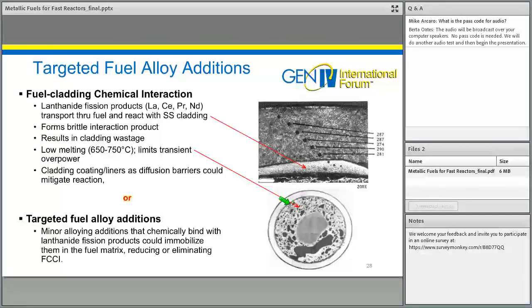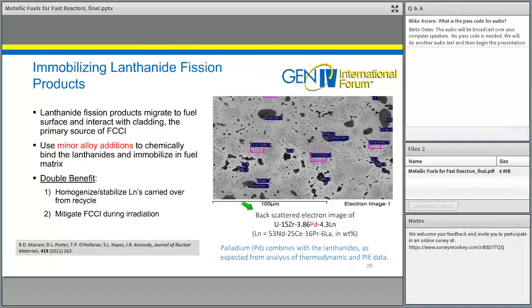These tend to have difficult fabrication processes. What we've been looking at recently are, well, we've been asking ourselves the question, is there an alloy addition I can make to the fuel, a minor alloy addition, that would react with the rare earth fission products when they're created, chemically bind with them in the fuel matrix, immobilize them, and if I can prevent them from ever transporting to the cladding surface, then I've essentially eliminated the FCCI problem at the source. So we're looking at a variety of elements that might be capable of doing that.